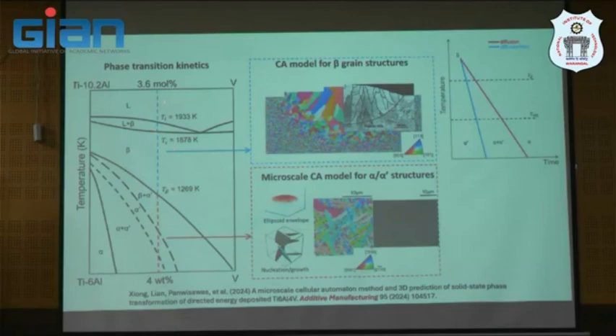follow this dashed line, when you become liquid here, it's liquid here, and then if you cool down the temperature up to the solidus temperature, you trap into this liquid plus beta grain zone. It's a bit of a mushy zone before you reach the solidus temperature. And this is the beta grain, which is BCC in nature. And once you reach about 1269 Kelvin, the beta transformation temperature, it transforms from beta to martensite, and then after that goes to lath martensitic